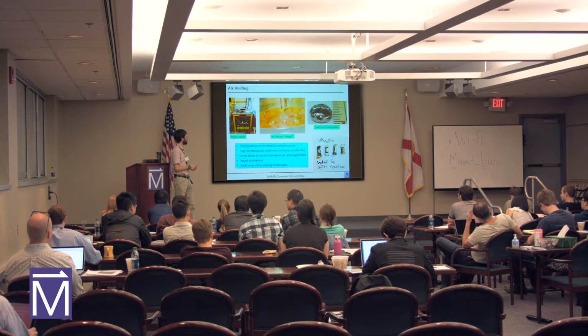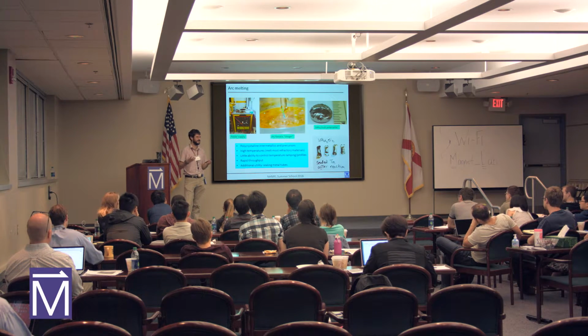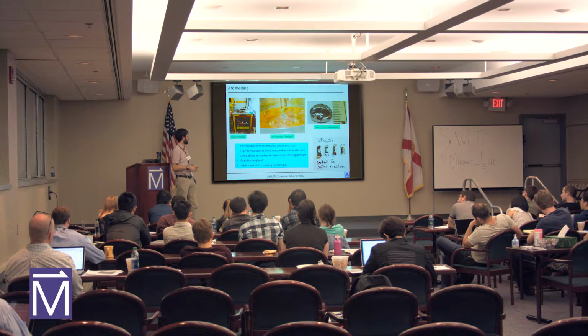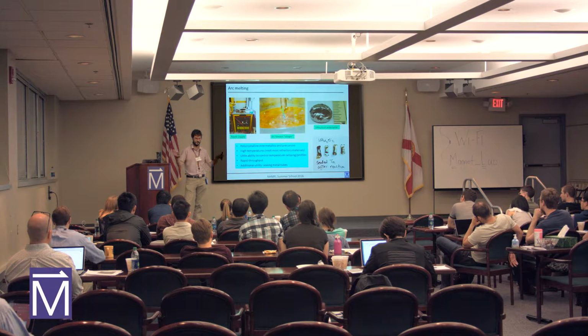Okay, and the way that you would make something like this is that you'd have a little bit of a strategy. You'd put the cerium and boron next to each other, because if you look at their binary phase diagram, how many people are familiar with binary phase diagrams? Okay, so one of the neat things about materials is that in chemistry, when you mix two materials together, it may turn out that the combinations of them could have lower or higher melting temperatures than the individual pieces. All right, and the place where those melting curves come down, if they do come down, is called a eutectic. So for instance, for cerium and boron, boron's a giant pain. I mean, if you just put boron in there and try to melt it, you're probably not going to succeed. But if you combine cerium and boron, actually the melting temperature falls down pretty far.